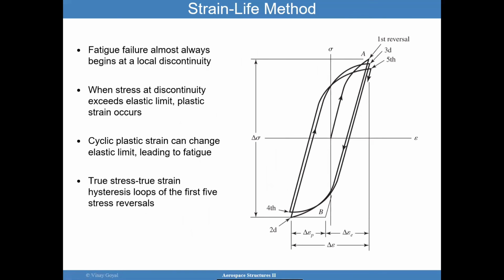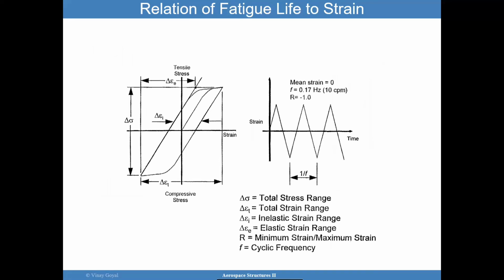The strain life method, basically, fatigue failure almost always occurs at a local discontinuity. When stress at a discontinuity exceeds the elastic limit, plastic strain will occur, like I discussed. The cyclic plastic strain can change the elastic limit, leading to fatigue. So it's true stress strain curve for the hysteresis. You want to do a modeling that accounts at least for 5 reversals to really understand that strain range that should be included in strain life methods.